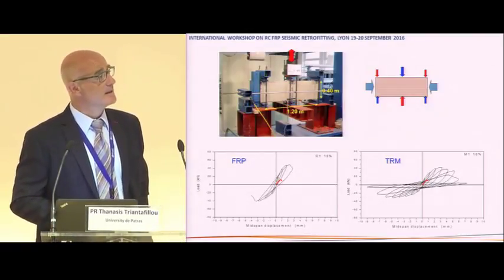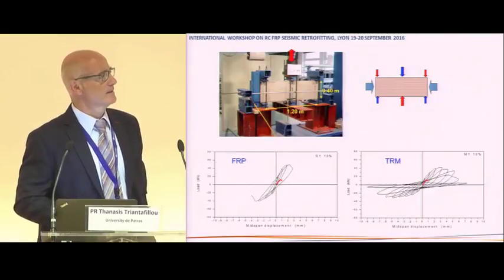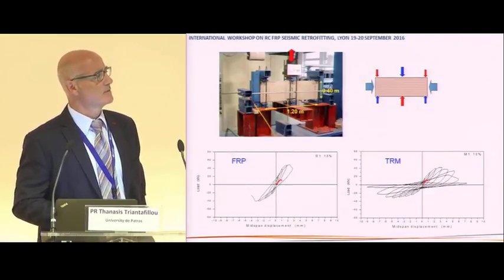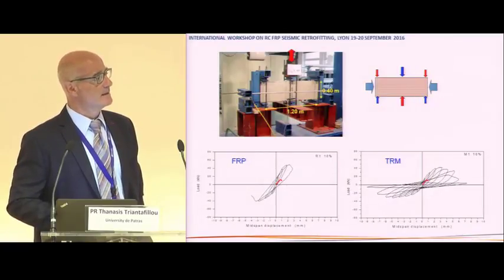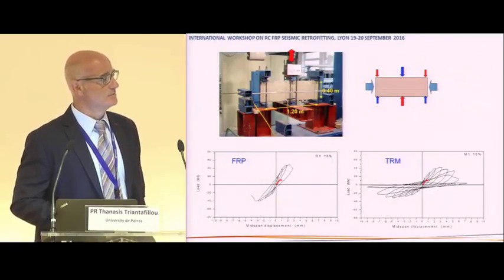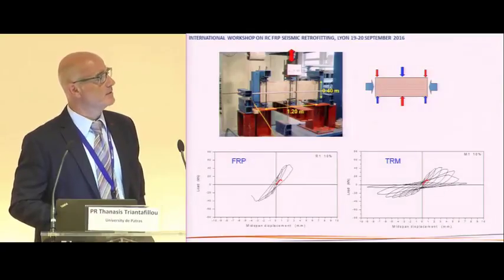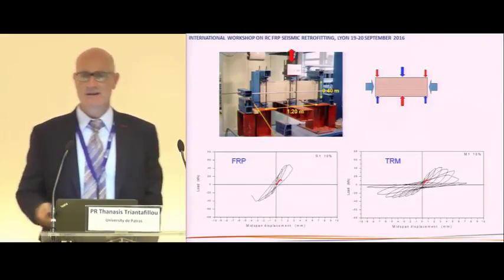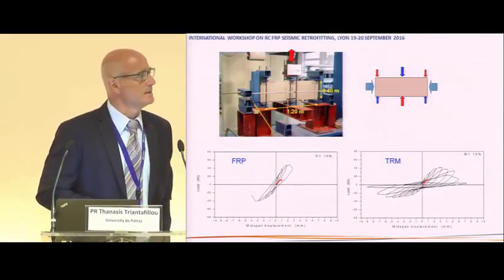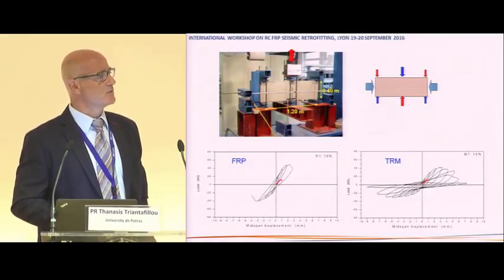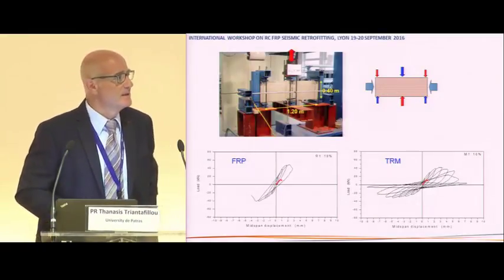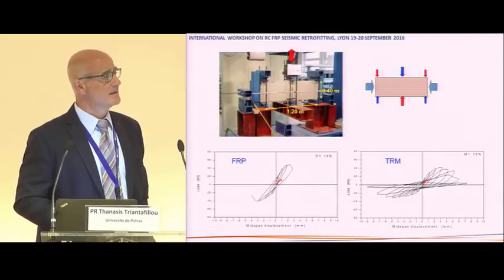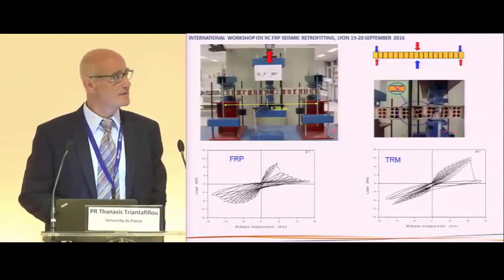This is an in-plane flexure of a typical masonry wall-type element, without any axial load. Again, red is what corresponds to the non-retrofitted wall. That's what we get if we use FRP, and that's what we get if we use the TRM. So the effectiveness of the two systems is very similar, and the ductility in general of the TRM system is even higher.